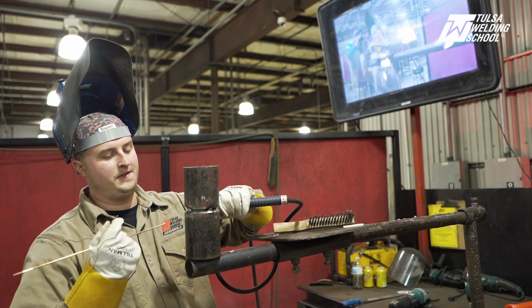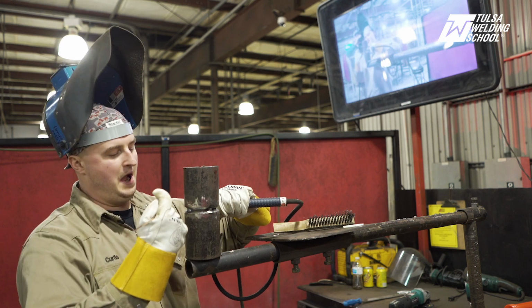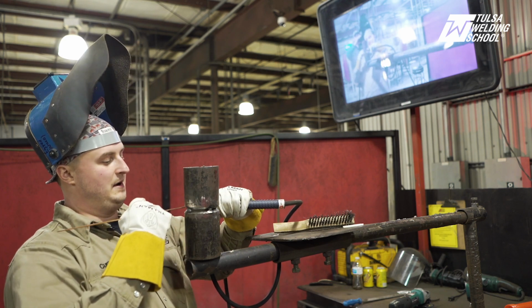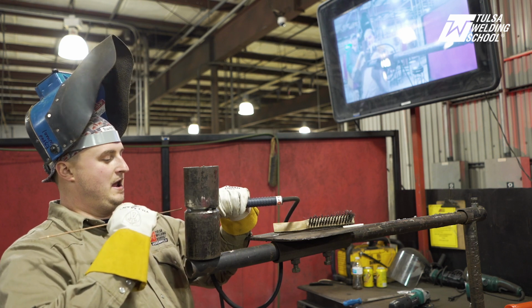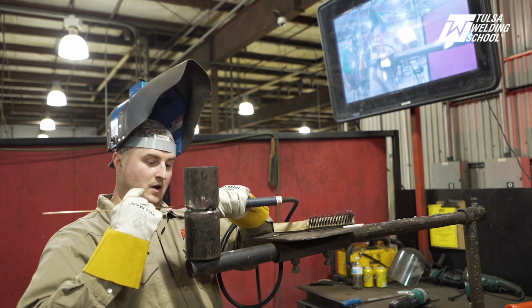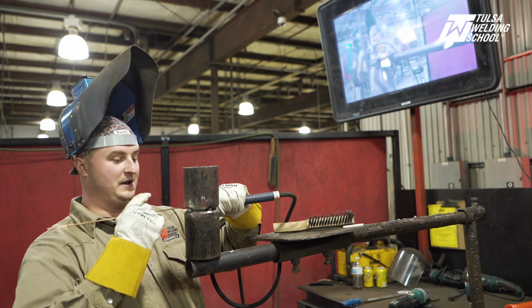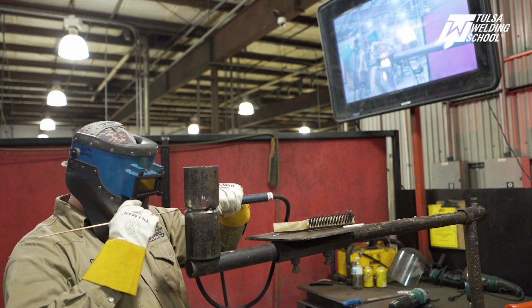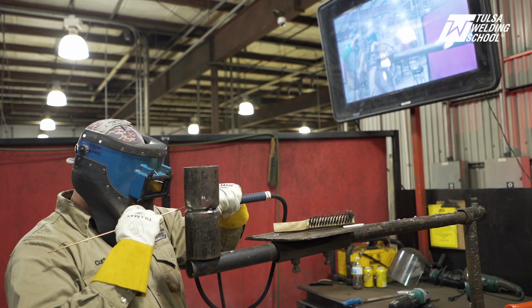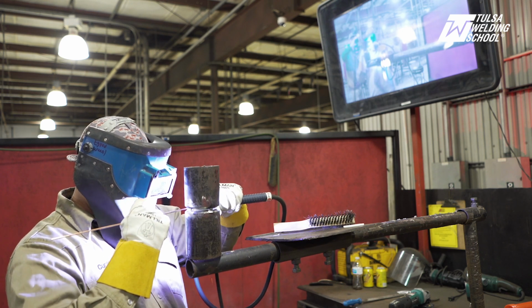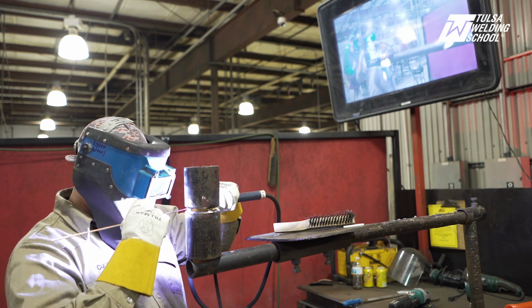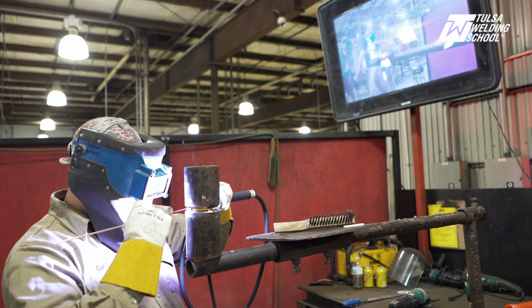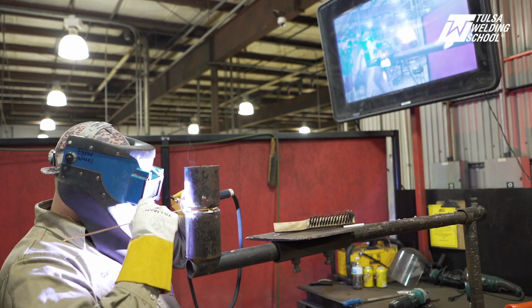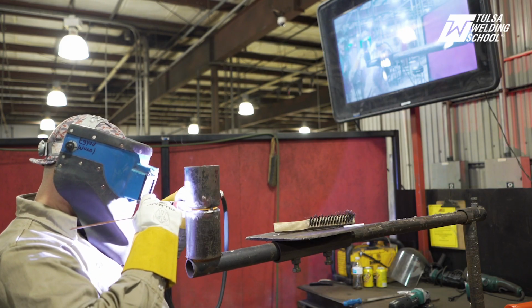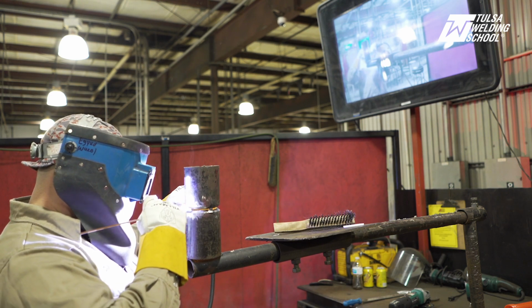And another really important thing on this horizontal is we want to stay out ahead of the cup as we're walking it. If we get to the point where we're right here, we're already behind the cup. We're starting to get in that red zone where we're going to get in trouble. So again, heat up my tack, I bring my wire in. Again, I'm flexing back on that wire, and I'm keeping that root pass nice and tight. I don't want to spread this out too much because I'll get sucked back on the inside of the pipe. So again, as you can see, I'm shuffling my feet around. I'm staying in front of it.